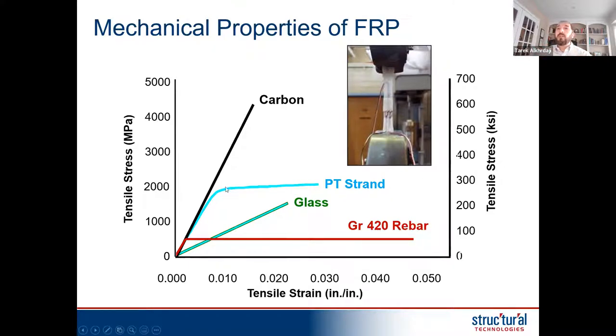If I compare that to, for example, post-tensioning cable, I get a much higher strength than steel bar, close to 1900 MPa. But then after that, I get some ductility. It's like pseudo ductility, because this can go up sometimes, the branch after yielding.